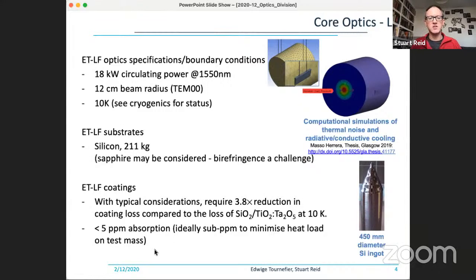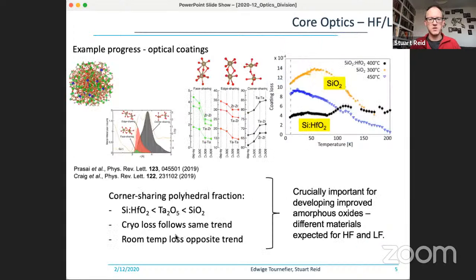That's in terms of the substrates and test masses, but in terms of the coatings, again, if we consider the same optical properties, then we require a 3.8 times reduction in the coating mechanical loss compared to current coatings at 10 Kelvin. Absorption, we expect to be set at 5 ppm or less, but the exact number for permittable absorption will be informed by the cryogenic and suspensions work that's being done. I just want to cite a couple of very important updates recently from within our community that informs where we might be going, in particular with the coatings.